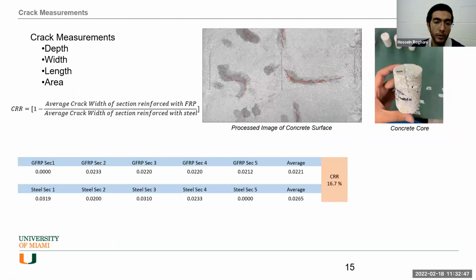And what we have done in terms of the quantification of the cracks. Here you can see some photos of the crack depths, crack widths, crack lengths, all those characteristics of the cracks. Each slab is divided into two parts. One part is reinforced with the FRP, one part is reinforced with the steel.